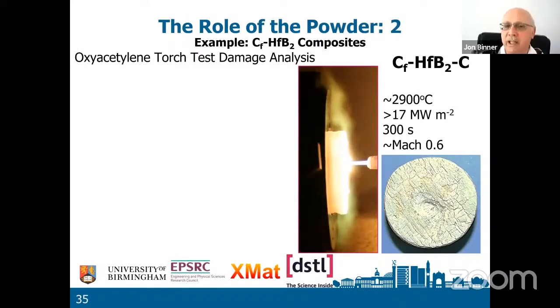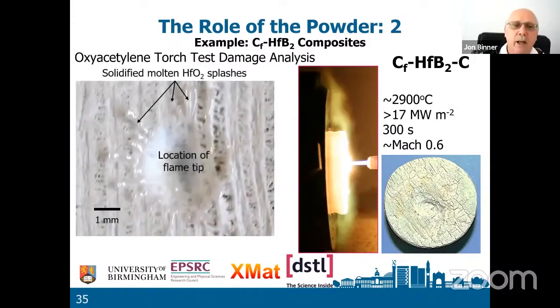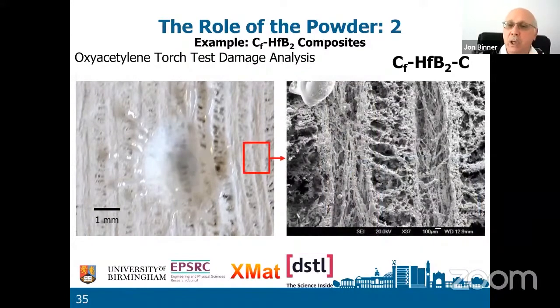Here is a material being tested. I'll explain more about the testing shortly. This is an oxyacetylene torch. But there's the location of the flame tip. You can see, I hope, some solidified material that used to be molten hafnia. And if we look at the structure of the material, you can see this is the fiber, preformed carbon fibers coated in what is now hafnia, what was hafnium diboride.